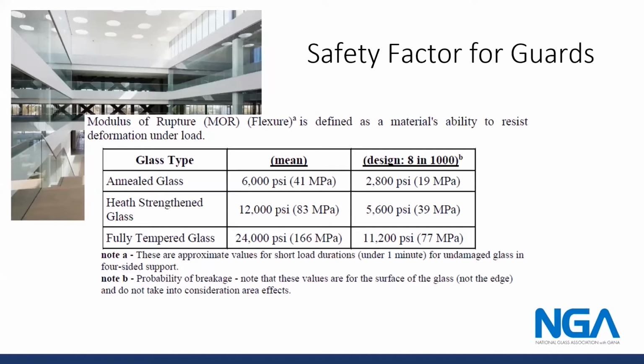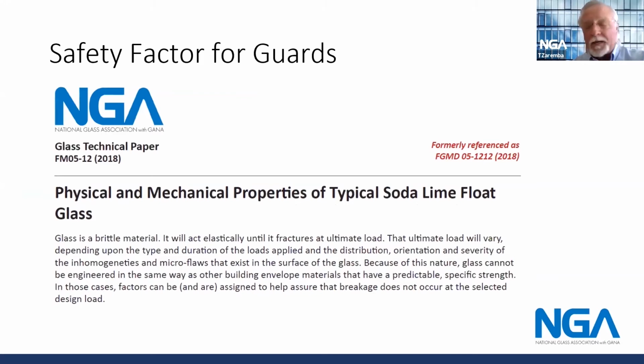But when you design the glass, you do not apply a factor of 4 to the design loads. Instead, the glass should be analyzed for each load, both the linear load of 50 pounds and the concentrated load of 200 pounds separately. And the resultant stress should then be compared to the glass strength values, which are published by NGA in a document, FM 05-12-2018. And then those values, as specified in the NGA document, should be divided by 4. So for fully tempered glass, the design stress should be compared to 6,000 PSI for fully tempered and 3,000 PSI for heat strengthened. As to any other types of materials that are used in the guards, they do not require a safety factor of 4.